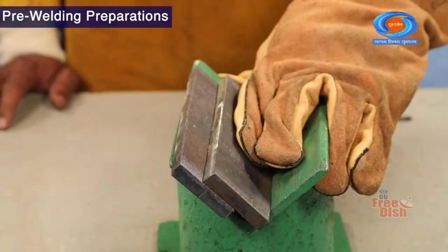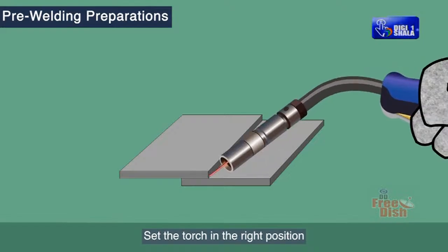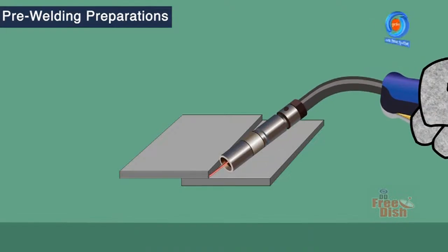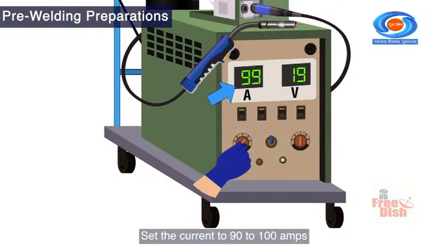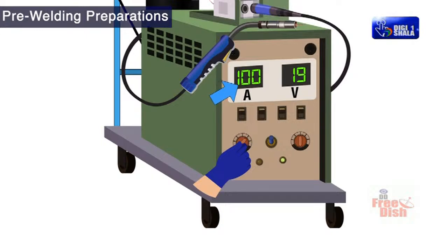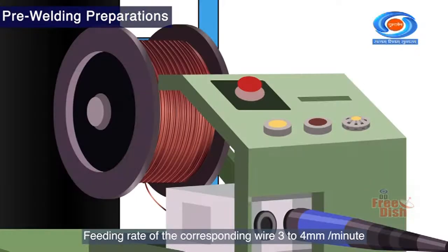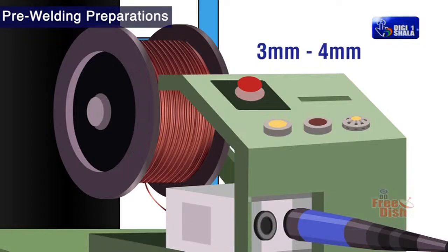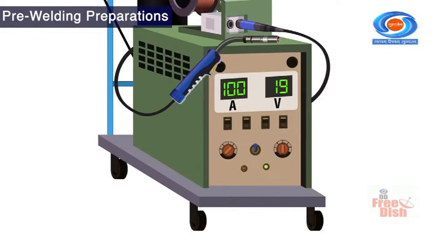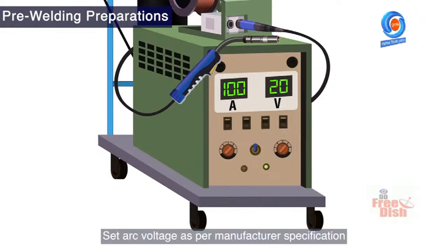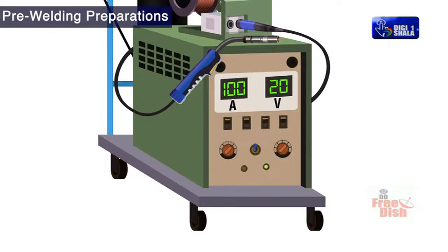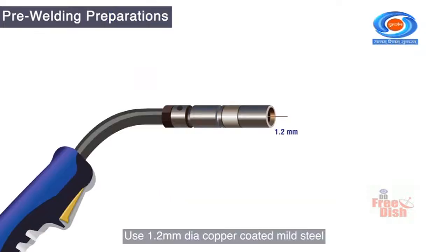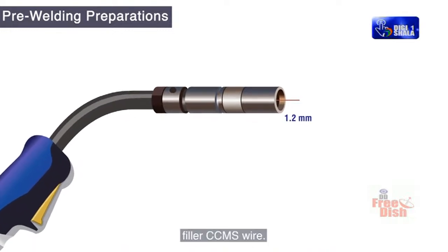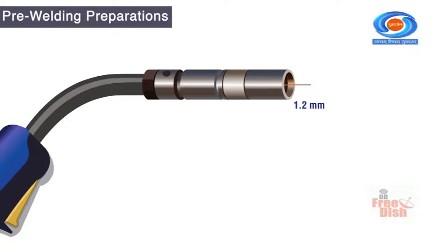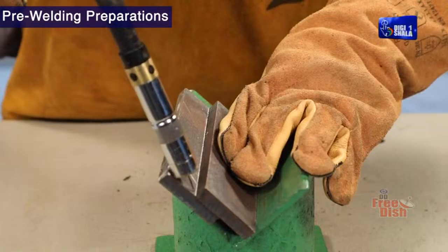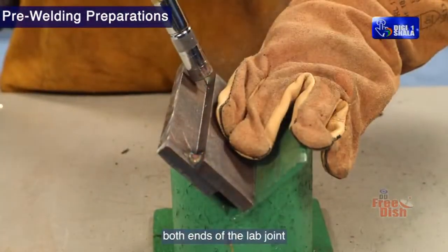Wear protective clothing. Set the torch in the right position. Set the current to 90 to 100 amps. Feeding rate of the corresponding wire 3 to 4 mm per minute. Set arc voltage as per manufacturer specification. Use 1.2 mm dia copper coated mild steel filler CCMS wire. On the welding table, tack weld both ends of the lap joint.